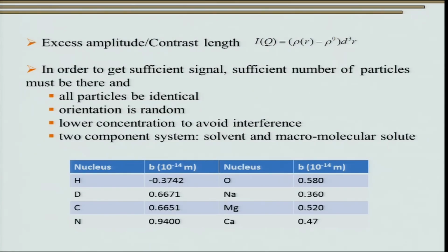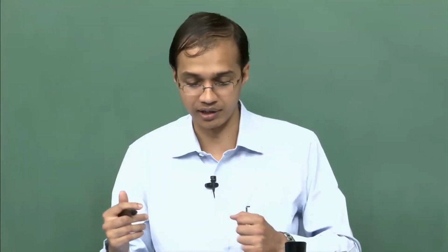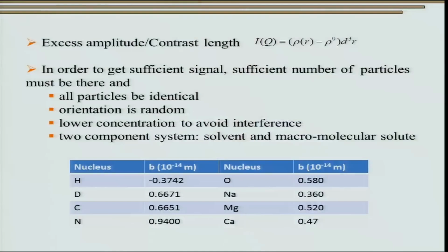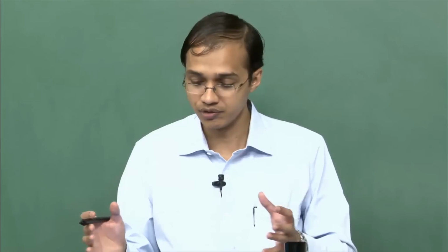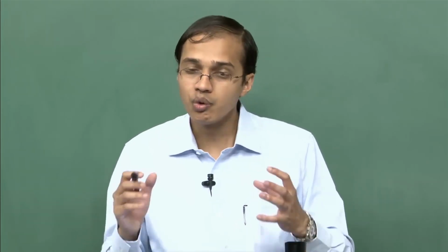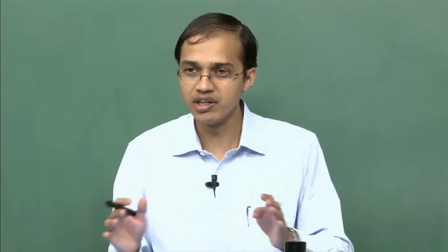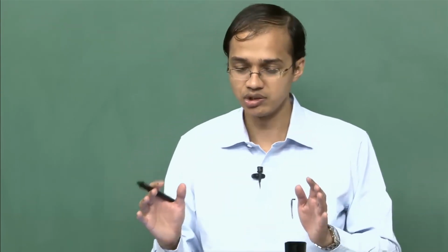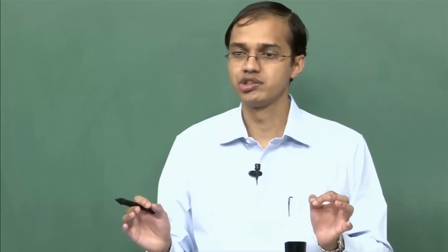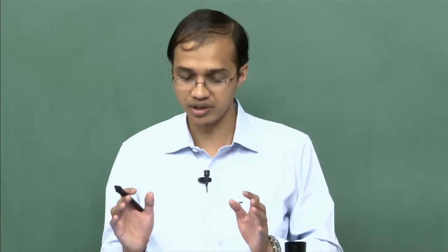We have lower concentration, so that there is no interference of scattering caused from one particle with that caused by the other particle. Another important thing is we ideally like a two component system, so you have a solvent and your particle, which may be a macromolecule. You do not like any interaction between these two and the presence of a third phase. In this case the situation is very clean and you can do very easy analysis of your sample and get information about the size, shape as well as distribution of the particle under consideration.